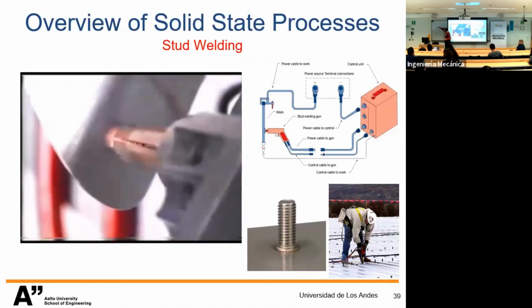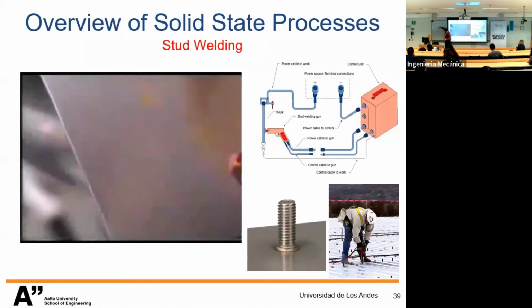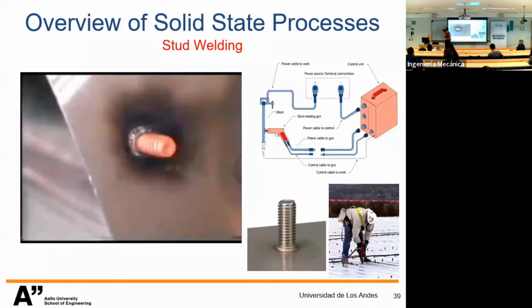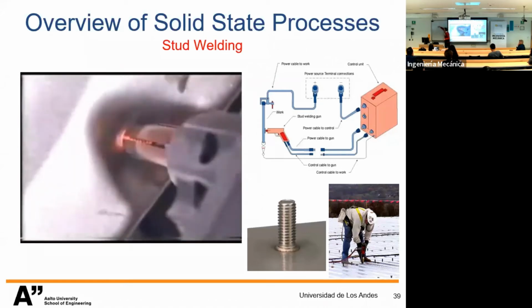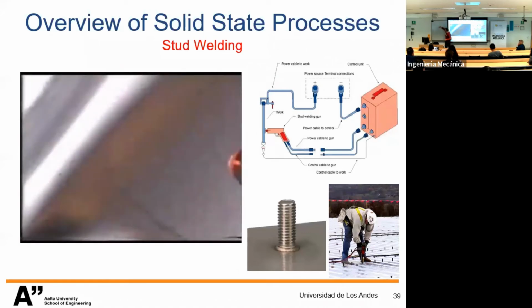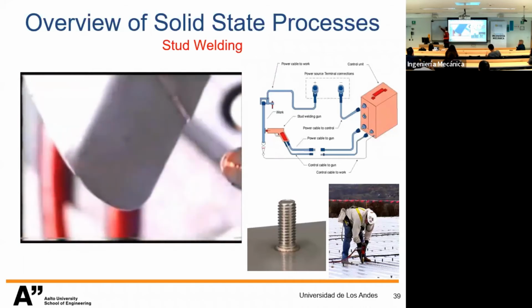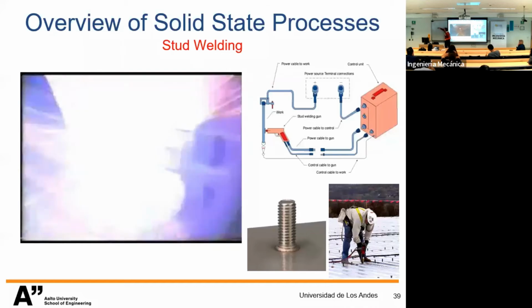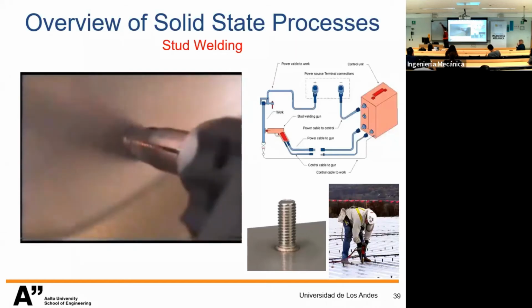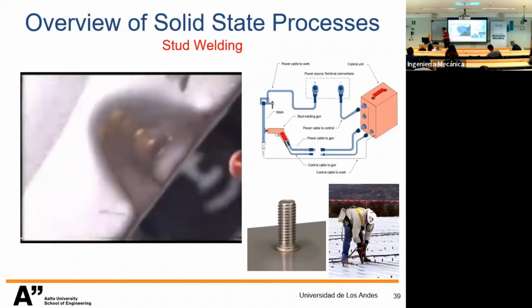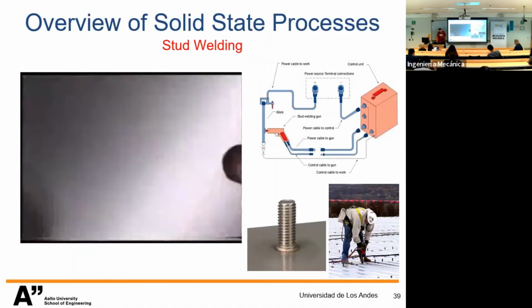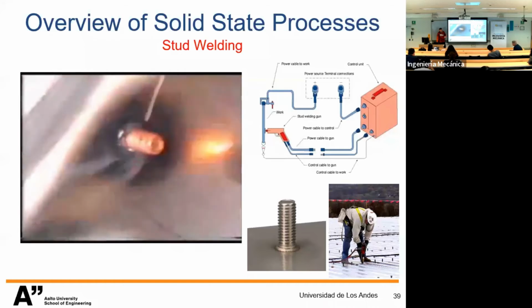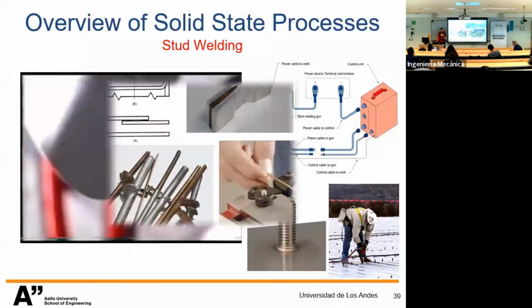You have the spark system, the liquidification of the surface, and then you destroy the mechanical gap providing the element of the stud. So the stud is not flat, there is a distance that is pre-established by the shape of the stud, and bringing them together, liquid goes out, and you have the high temperature under pressure, generating and sometimes the activation of joining mechanisms and these new chemically activated surfaces.